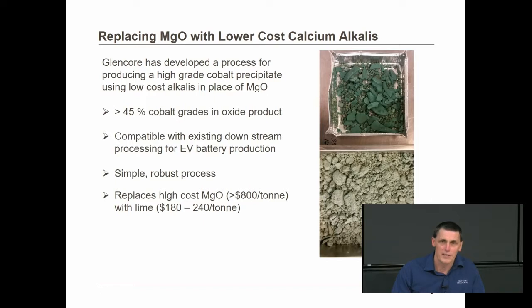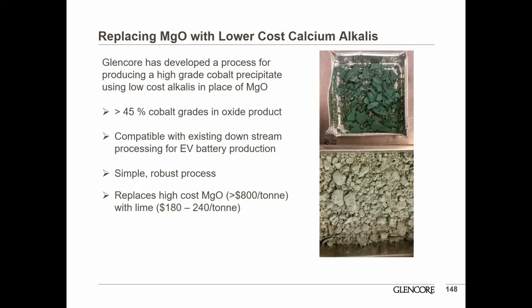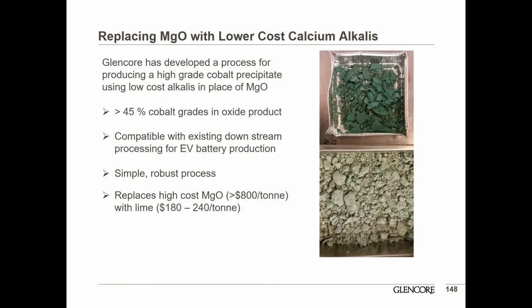What we've found is that we can replace the high-cost magnesium oxide with low-cost lime and part of the neutralisation with limestone. What this gives us is a blend of cobalt oxide, cobalt hydroxide and gypsum. But by controlling the conditions properly and by favouring gypsum growth, we can get quite a significant size difference between the gypsum and the cobalt product. And through simple separation through a cyclone, we can produce a 45 to 50% cobalt product consistent with what will be produced in the magnesium oxide circuit, and separate a gypsum product out at about a third of the cost of operating that circuit. So this is a significant step forward and one that we've developed specifically within our operations over the last 2 or 3 years, and something that we're quite happy to work with our external clients on.